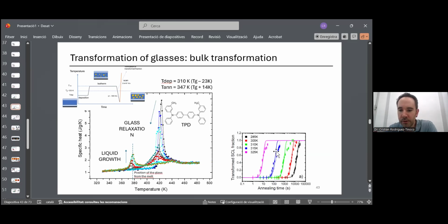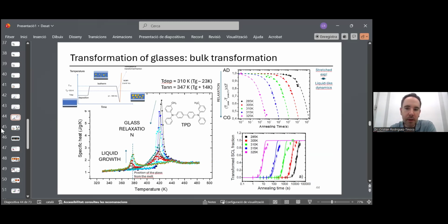And this is how it looks for different stabilities. Okay, this is fitted with an Avrami, which is not a perfect fit, but just to have an idea. For the most stable glass, we have this black point here. You see here, we have to wait for almost 10 to the 4 seconds before we start seeing some supercooled liquid, okay? Which means before some liquid appears in the glass, okay? And then once it appears, the amount of liquid increases until everything has been transformed, okay? And this is for different glasses, different stabilities. The lower the stability, the closer to the glass transition temperature of the TPD, the smaller is the annealing time required to become a liquid. And also, this is the position of this peak. This is also relaxing. I will not go into detail about that.